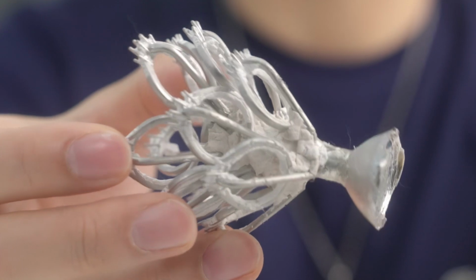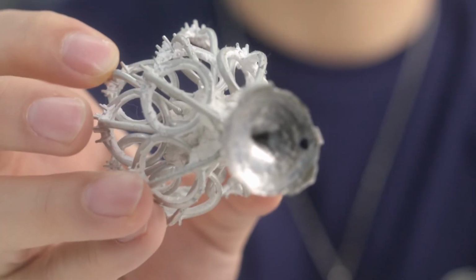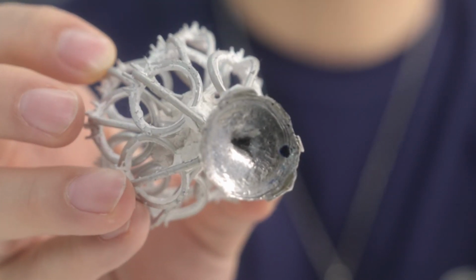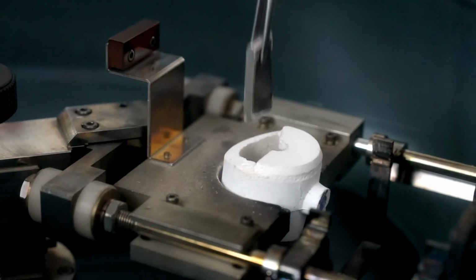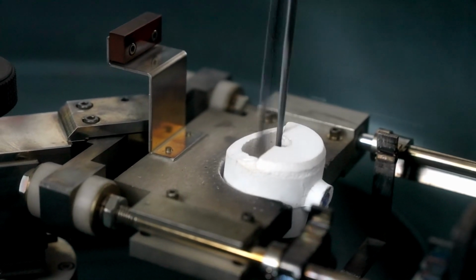Well, we often mix reused material with 30 to 50% new platinum with every new casting. The reason behind that recommendation is to counter issues of contamination, such as silicon that found its way into our metal, just to dilute it out with the addition of new platinum.